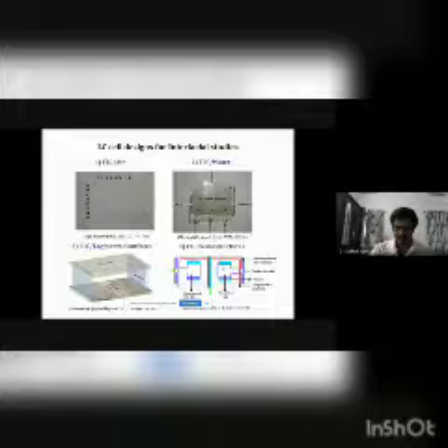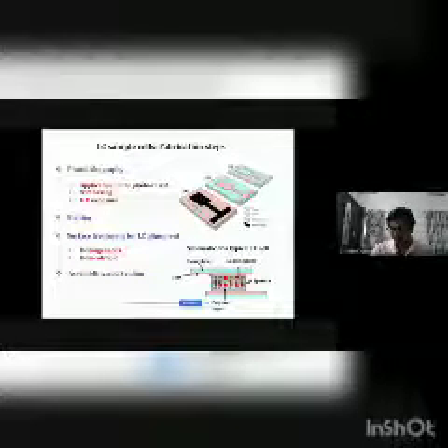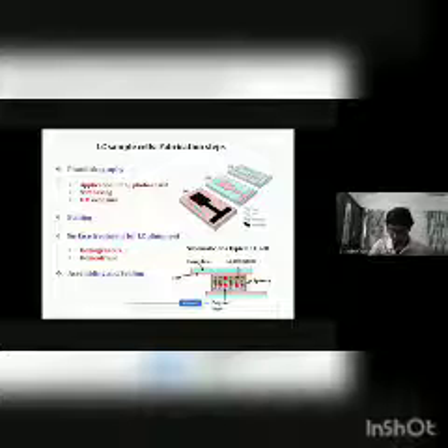So mainly we are giving two types of surface treatment. One is homogeneous and the other is homeotropic. And typically you can see that this will be the orientation of the totally assembled liquid crystal cell. We will have two ITO coated glass plates with a spacing. A spacer of normally 3 microns will be used, and in between these two glass plates you can fill the material by using capillary action.